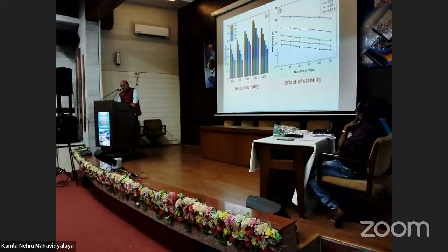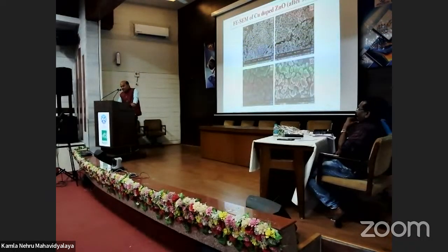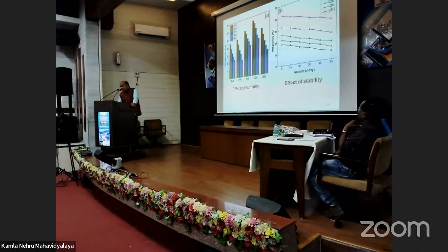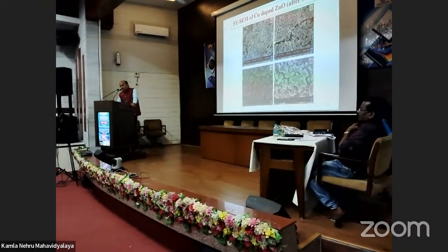Humidity tested: 11% humidity is the working humidity condition for this particular sensor, and stability we have tested. Stability is up to 50 days. After sensing, we verified the morphology of the material. The material does not lose stability. We can go on using this particular sensor for sensing purposes.